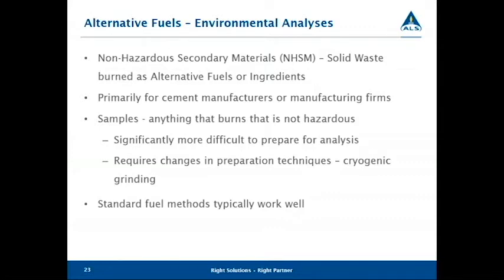The preparation process on these is really difficult sometimes, and it's very time consuming on some of these unique samples. And typically most of them will require cryogenic grinding, which means that we first freeze the sample with liquid nitrogen before we grind it. For the fuel quality analysis, the standard fuel methods work very well with these types of samples.